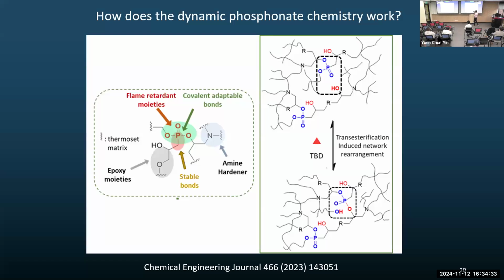So the first chemistry is, in the beginning I showed you people have come up with all kinds of covalent adaptable network chemistry. So we were the first one to develop this phosphonate chemistry. A phosphonate chemistry is phosphorus based. You can see phosphorus is linked to 2 labile PO bonds and 1 permanent carbon bond. So what we do is we fix this chemistry inside the thermoset resin by playing some trick. I will show you how we do it. And the fact that there are 2 labile bonds and there are alcohols sitting around it, you actually can do a reversible reaction. So these are phosphoester reactions. You can see on the right, an alcohol is attacking the existing phosphoester bond, and you make a new bond. While the new bond is being made, you soften the material and you can reprocess it by thermal action.